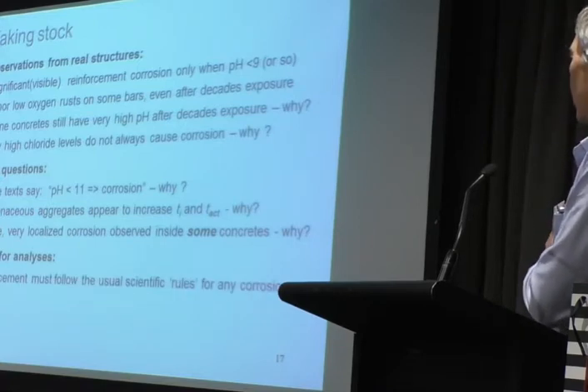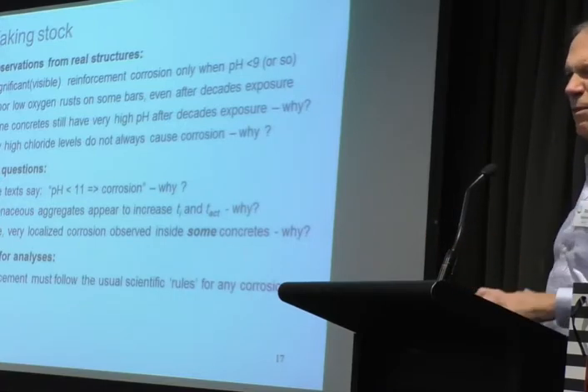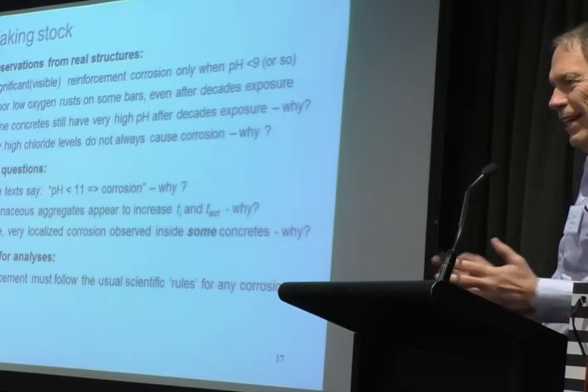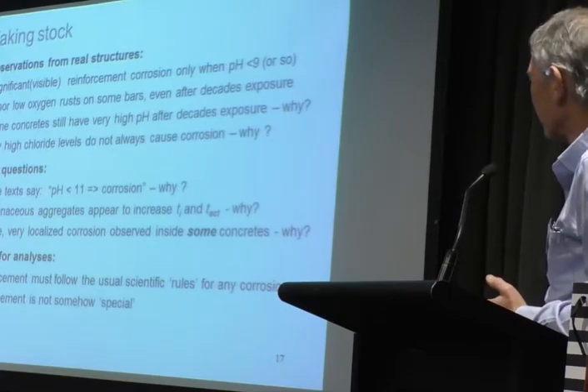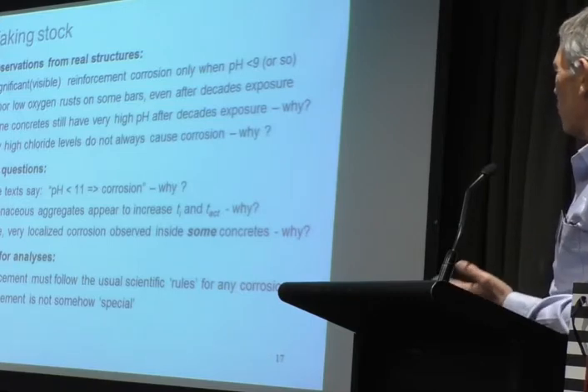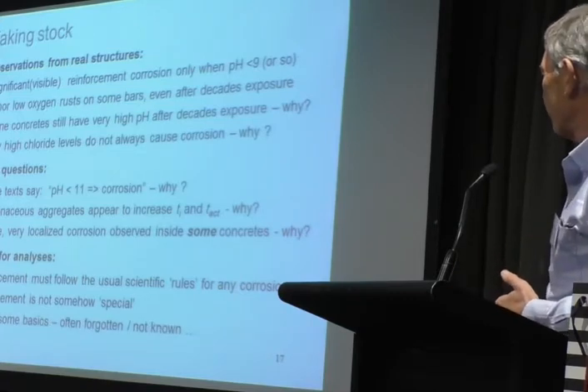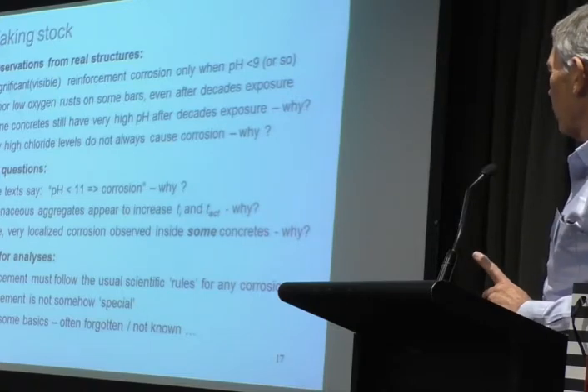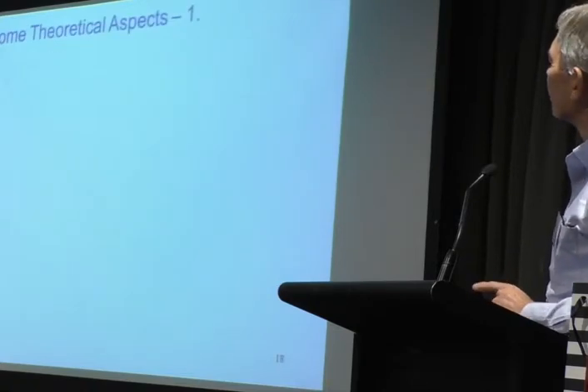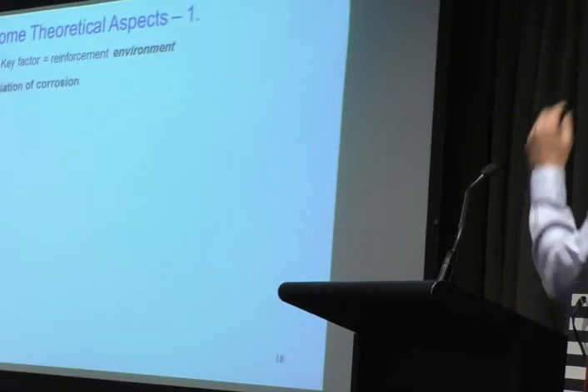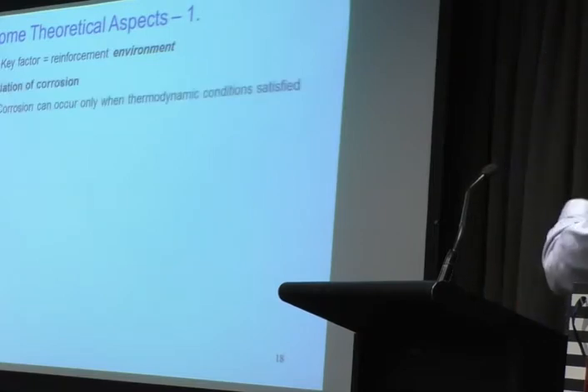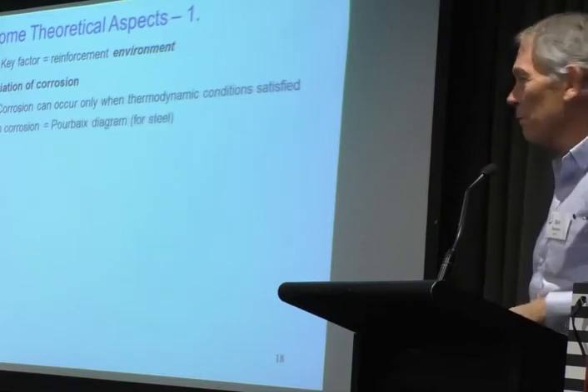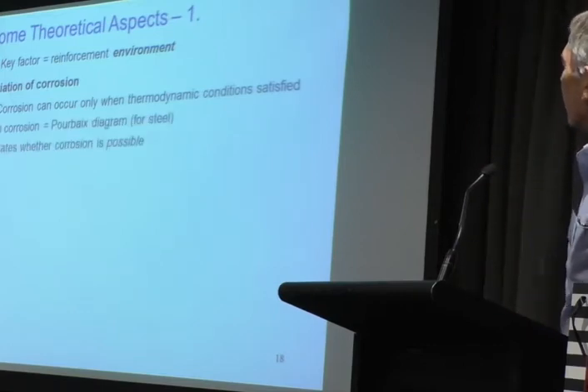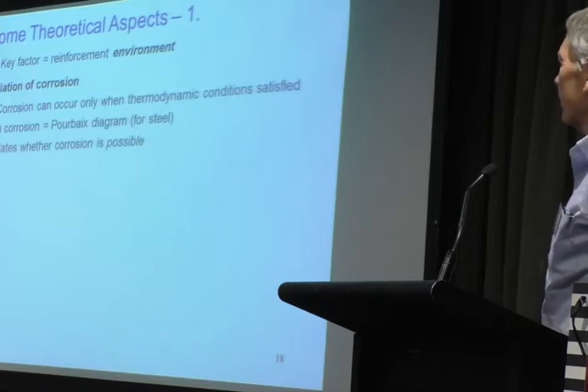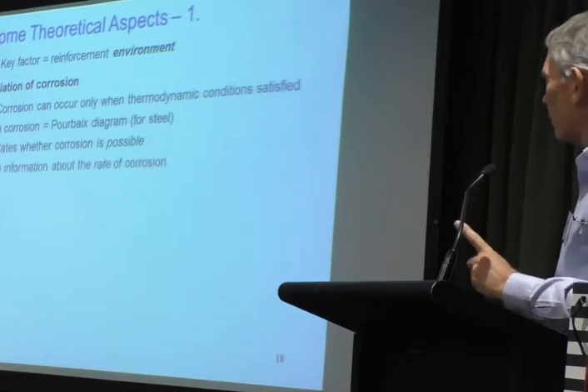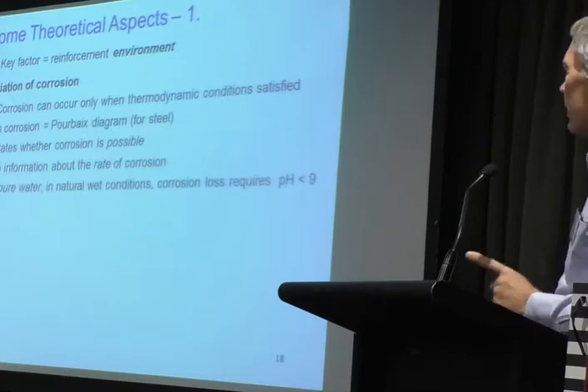So the way we thought about it was, well, reinforcement corrosion isn't all that different from any other corrosion, it's just that the environment's different. So the same sort of rules must apply. It's not somehow special. And there are some aspects that I think sometimes we forget. The key factor is the environment. Initiation of corrosion can only occur when those thermodynamic requirements, the Pourbaix diagram and so on, are satisfied. And that tells you, as we've already been told this morning, it's only when corrosion is possible, not the rate. And that's the bit that really is important for us.